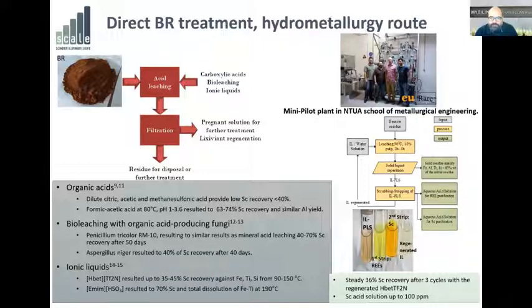which has the added advantage that you can recover the ionic liquid at the end of the cycle. So you mix the ionic liquid with water, you leach the bauxite residue, you separate your solids, and then you strip the ionic liquid phase from the water and the scandium and the rare earths, and regenerate the ionic liquid. It works kind of like a solvent extraction in the last step, so you can increase by a lot the concentration of scandium. We have managed to increase it up to 100 ppm, starting from a solution that had something like 5 ppm of scandium. Of course, the recovery of scandium is still 30 to 36%, but you are now able to have a solution that has much higher scandium and rare earth contents.